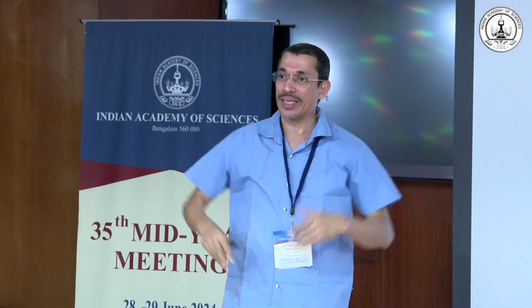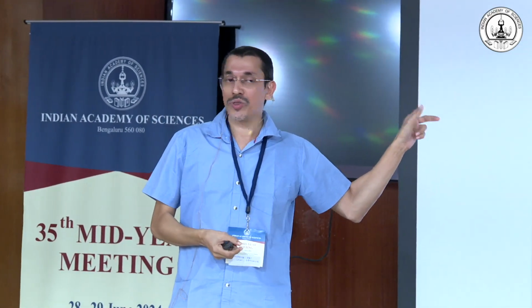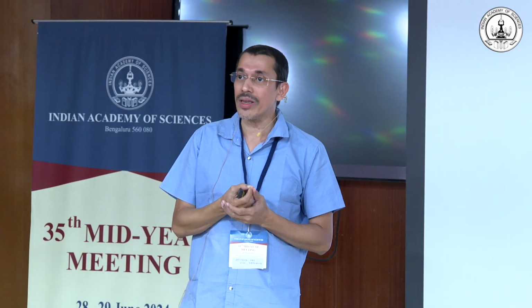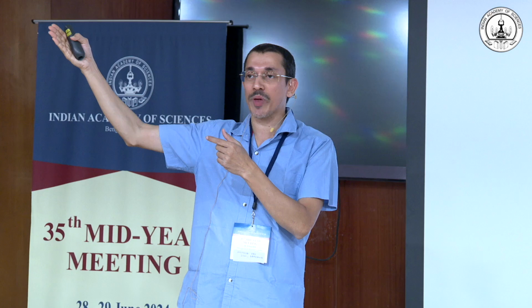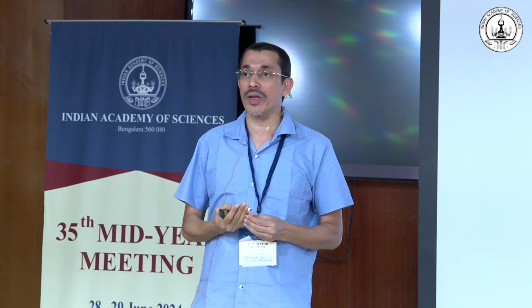So it requires lots of averaging to get the data. The accuracy depends on how long you are averaging. For the data which I showed you, each data point we averaged almost a few hours to get decent data. So in this experiment our resolution may be of the order of 10 millikelvin, but there are other experiments like quantum Hall where we use this same thermometry. There we have gone to less than 1 millikelvin accuracy for delta T.